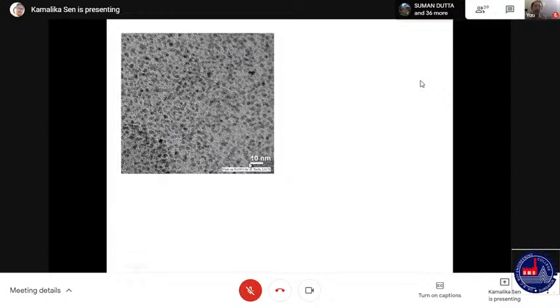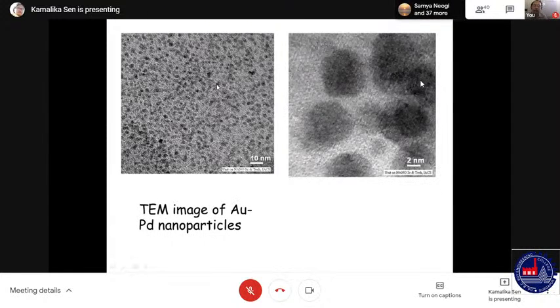This was the TEM image which showed very small particles. You can see 2 to 3 nanometer size gold-palladium bimetallic nanoparticles. If I zoom in, you can see a darker shade, which is possibly because of the gold, and the light shade, which is because of the palladium, and even mixed shades, which show there is also the presence of alloy type nanoparticles.